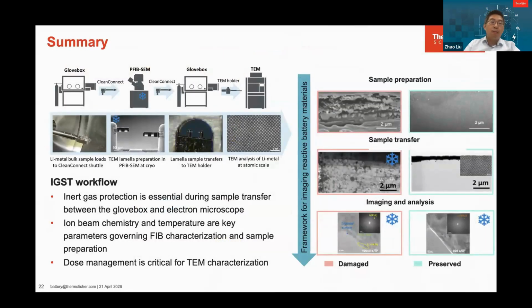So in summary, in my presentation here, I just showcase IGST workflow is very critical for the sample transfer. And during the FIB-SEM, you need to really consider the chemistry and temperature as a parameter that can cause sample damage. And finally, in the TEM cryogenic temperature, TEM is not always the only answer. You also need to be very careful about the dose in the characterization part.